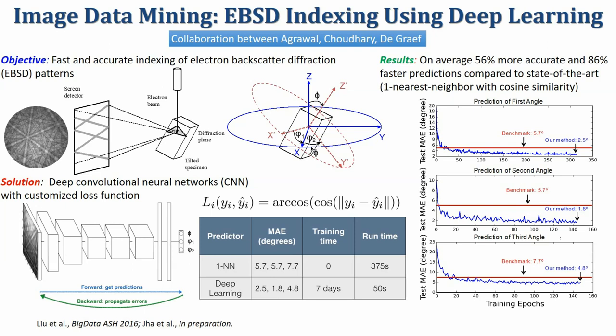The loss function had to be customized in this case because although these angles are numbers, they are not like ordinary numbers. So 1 degree is very close to 359 degrees, right? So you can't just use mean absolute error or mean square error to optimize this. So we use this cos inverse of cos of the difference, which maps everything into 0 to pi. And then this is the nearest neighbor approach, which they currently use. They call it the dictionary-based approach, where you get a new EBSD image, you just do a dot product of that image with your dictionary, which has all possible EBSD patterns, and then find the closest one. So these are the kind of errors you get with that approach, and with deep learning you can get much better and faster, at the cost of training, of course.